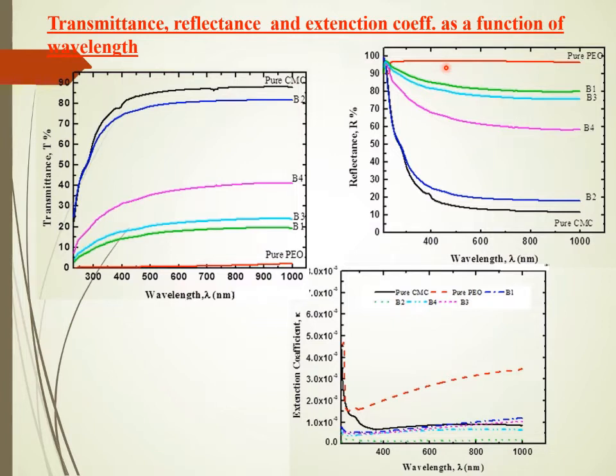Also, the figure indicates that a strong change happened in the transmittance, reflectance, and extinction coefficient of pure CMC and pure PEO as a result of blending. And also that the sample B2 has the highest transmittance and the lowest reflectance, and this sample consists of 80% CMC and 20% PEO.